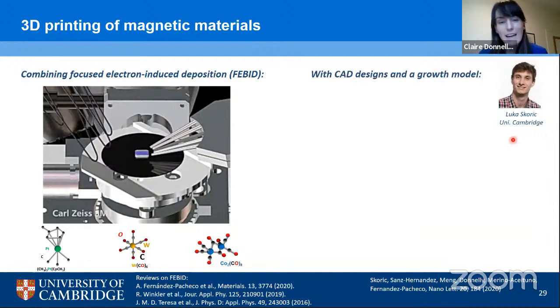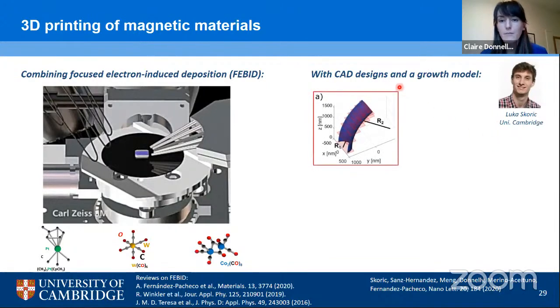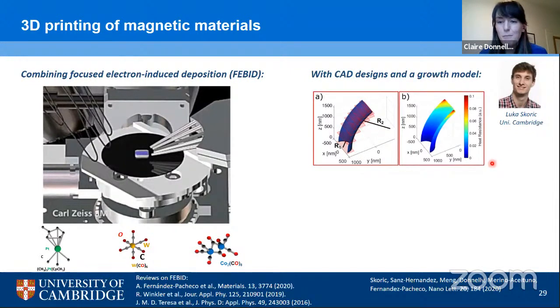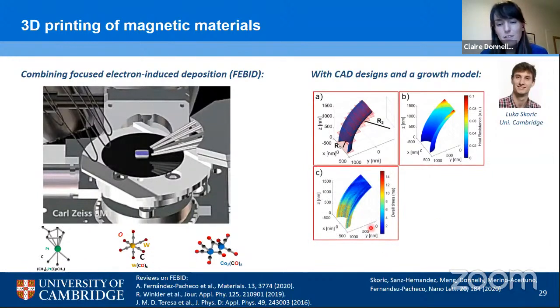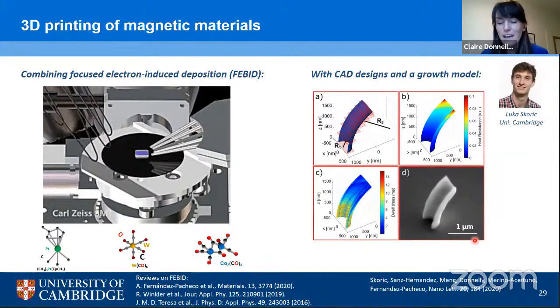So now onto how Luka has combined FEBID with a 3D printing methodology. He's combined essentially CAD designs with a robust growth model of FEBID, and in this way can achieve a 3D printing technique. So essentially what we do is we take our CAD design, we slice it up as you would do normally in normal 3D printing. Now Luka then combines the growth model with calibration measurements that you also perform to determine a set of scanning instructions for the microscope. You tell these to the microscope, and in the end, you can obtain a very high spatial resolution three-dimensional structure that is very accurate, very similar to what the original CAD drawing was in the first place.